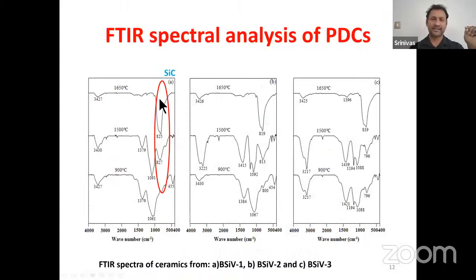In the FTIR spectroscopy also, the region around 1000 is the Si-O-Si linkage, and the region around 830 is SiC formation. Around 900 degrees, SiC formation is very less. If you go further, both SiO and SiC are there. In the second spectrum from the bottom, you see 1090 and 827, which means SiO and SiC coexist. With heat treatment at 1650 degrees centigrade, complete formation of silicon carbide can be seen in the IR spectrum, with evolution from SiO to SiC phase in all three systems.